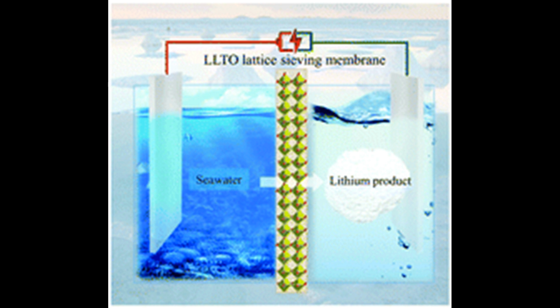Herein, we creatively employed a solid-state electrolyte membrane, and designed a continuous electrically driven membrane process, which successfully enriches lithium from seawater samples of the Red Sea by 43,000 times, i.e., from 0.21 to 9013.43 parts per million, with a nominal Li/Mg selectivity greater than 45 million. Lithium phosphate with a purity of 99.94% was precipitated directly from the enriched solution, thereby meeting the purity requirements for application in the lithium battery industry. Furthermore, a preliminary economic analysis shows that the process can be made profitable when coupled with the chlor-alkali industry.